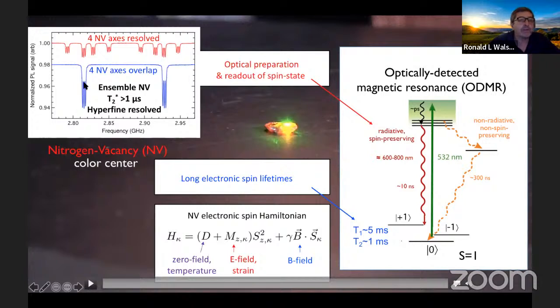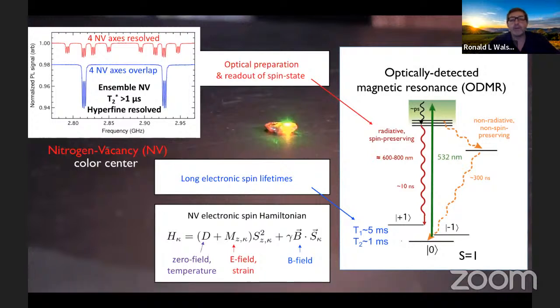In the actual measurements that we do, there's information in each of these dips and each of these sharp variations. And so if we're looking for small changes in fields, we'll often be dithering across these different sharp features, and we're looking for very tiny changes in these features. So we don't typically scan across the entire spectrum. Once we know where the features are, we sit right on the edge of these and we look for small changes in the fluorescence, which can give us information about small changes in the magnetic field, either with position, if we're doing an image, or with time, or both.